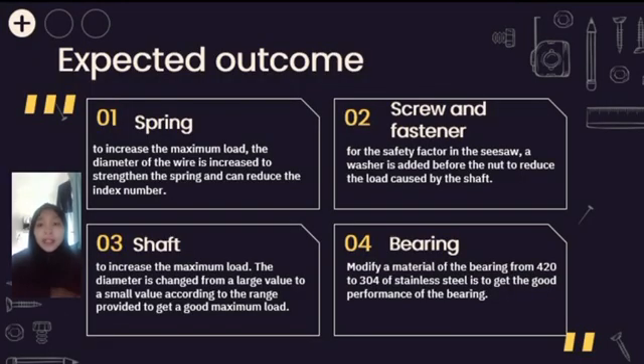Expected outcome. We explain the improvement and modification for four components, which are spring, screw and fastener, shaft and bearing. We go one by one. Spring. To increase the maximum load, the diameter of the wire must increase to strengthen the spring and reduce the index number. Screw and fastener. For the safety factor in the seesaw, a washer must be added before the nut to reduce the load caused by the shaft. Shaft. To increase the maximum load, the diameter must change from a large value to a small value, according to the range provided to get a good maximum load. Bearing. Modifying the material of the bearing from 420 to 304 stainless steel is to get good performance